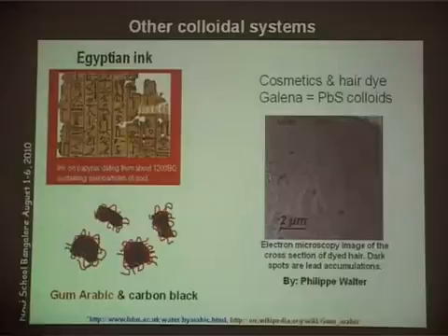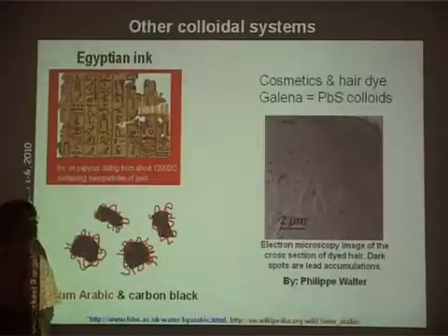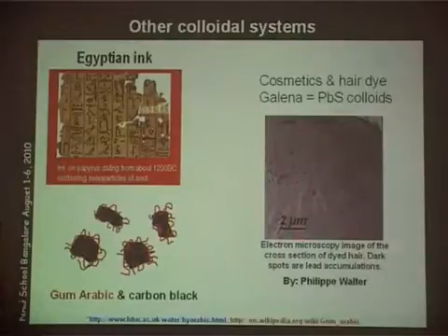And also the ancient Egyptians and Romans used something that you wouldn't like to do today, but at that time it was very fashionable to blacken your hair, especially when you get older. Some people suffer from getting white hair. They used at that time galena, which is a lead sulfide colloid, very small, of a few nanometers, and these black dots here, this is a cross-section, electron microscope image of a cross-section of a hair that had been dyed with that. You see these black dots, these are all these colloids that had accumulated in that piece of hair. So you can blacken permanently your hair for a long time with this material.